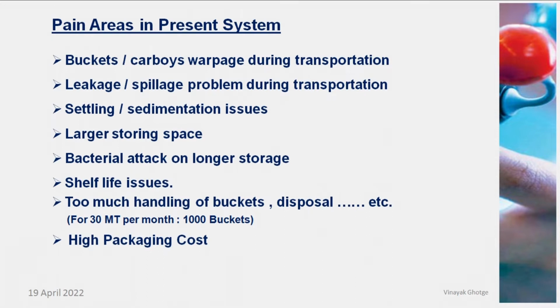Too much handling of the buckets. Most of the automotive foundries or the bulk coating consumers use coating to the tune of 30 to 50, 60 tons per month. So the number of buckets handled is quite high, and that's really a non-value added job. And of course, the high packaging cost. When I say high packaging cost, for the kind of water-based coatings being used by most of the automotive foundries for general purpose and for critical applications, about 15% of the selling price of the coating constitutes packing cost.